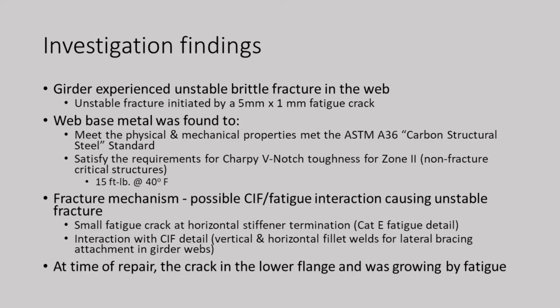We didn't have quite enough material. The plate was only 3/8 of an inch thick, so we couldn't do a full thickness Charpy. We had enough material for one subsized Charpy, and we ran it at the zone 2 temperature requirement, which covers that bridge. It's non-fracture critical, and we got a very low value, about 6 or 8 foot-pounds. And we were kind of alarmed at that.